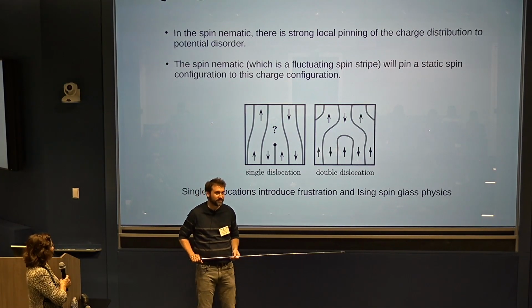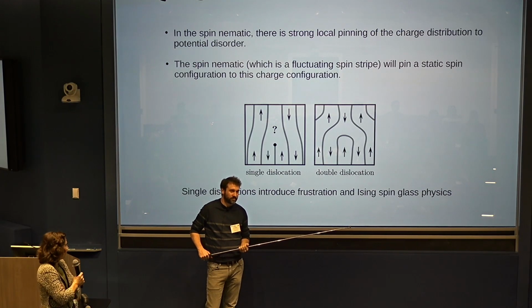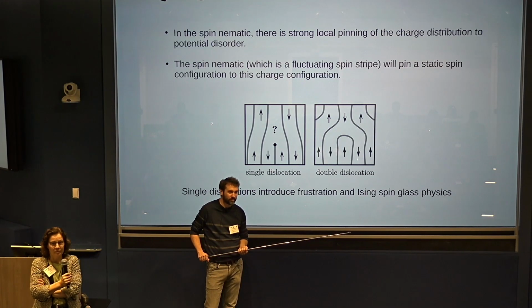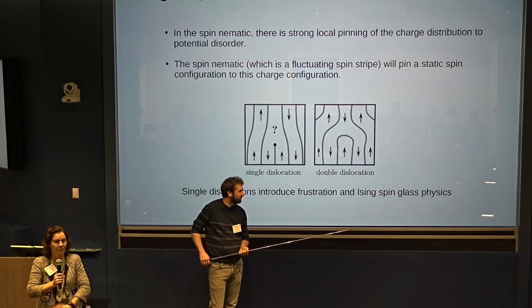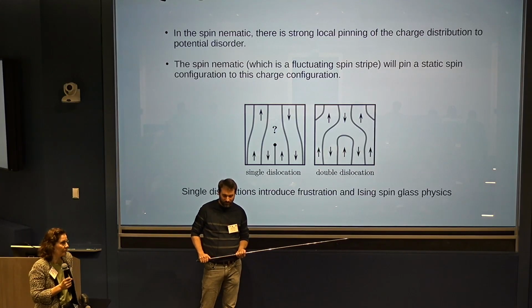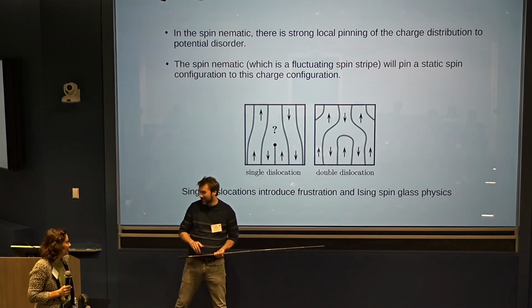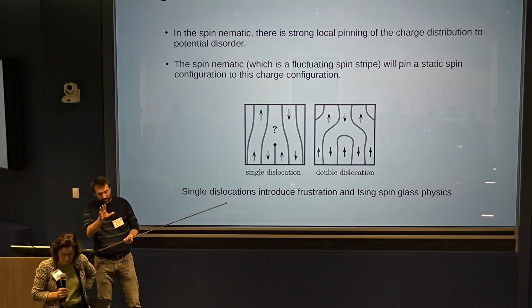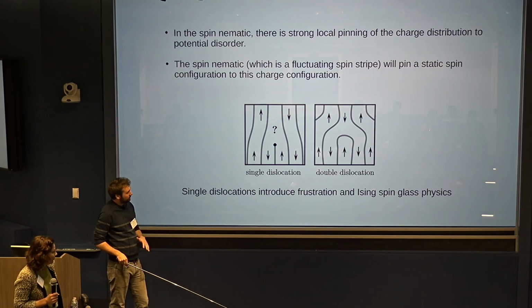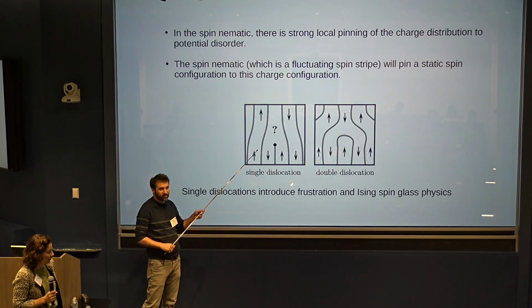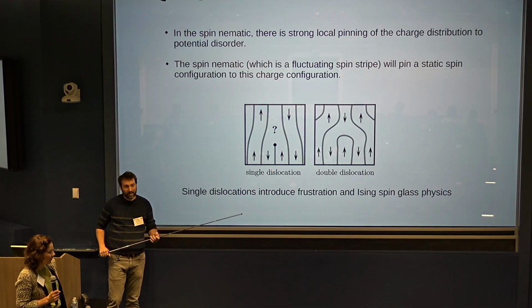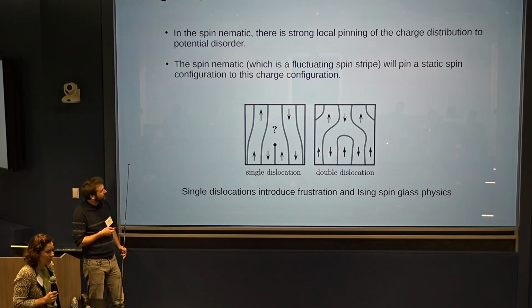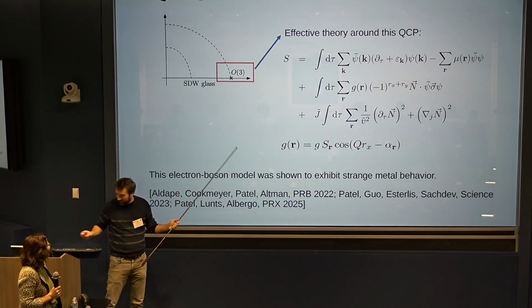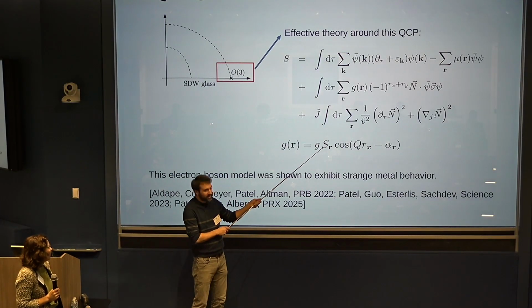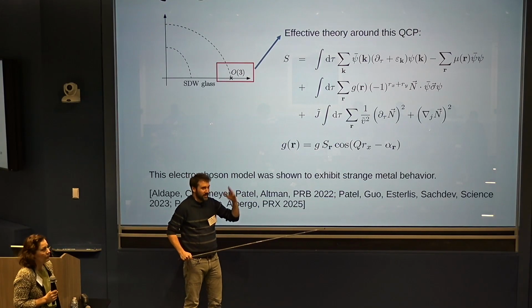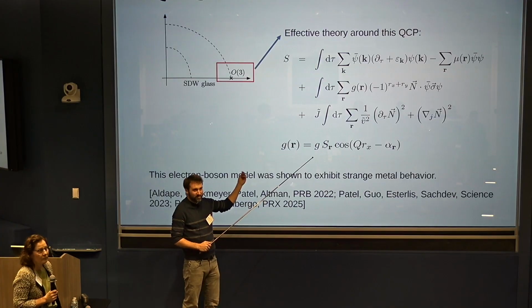spin glass. I'm not sure, but it means that there is also a breaking of rotation symmetry about the Ising axis. Yes. And I agree. Actually, we cannot rule it out completely. But I think the main point is that even if that were to happen, another possibility is that if you have very slowly varying disorder, there are almost no dislocations at all. That could also be a possibility. But actually, none of that really matters. You would still have basically the same theory. Just that this S would not be an Ising spin glass, but could now be more general. It doesn't really change the main message of the story.